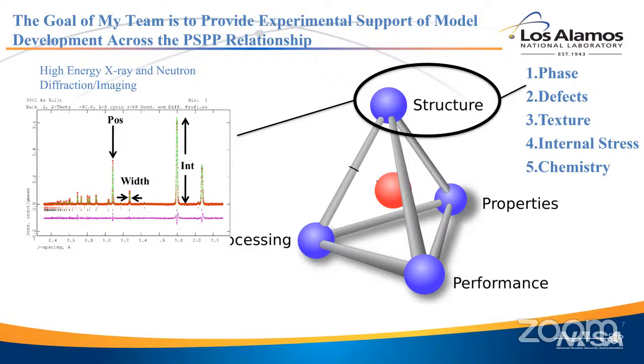We try to understand how processing affects structure and that impacts properties by pulling out microstructural features using diffraction. The nice thing about neutron and, more recently, high energy X-ray diffraction is it gives you that window onto the microstructure non-destructively. So I can look at a material as it's actually performing. I can do a tensile test and take diffraction while the tensile test is happening and watch how the microstructure is responding to that environment. And that's what our team does.